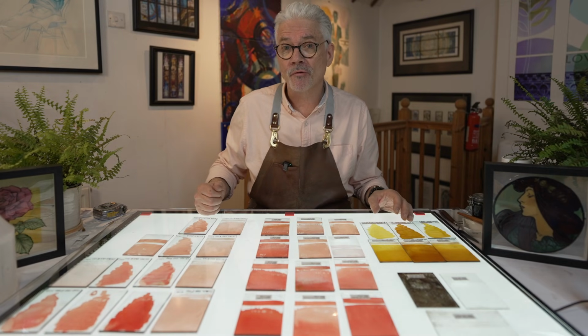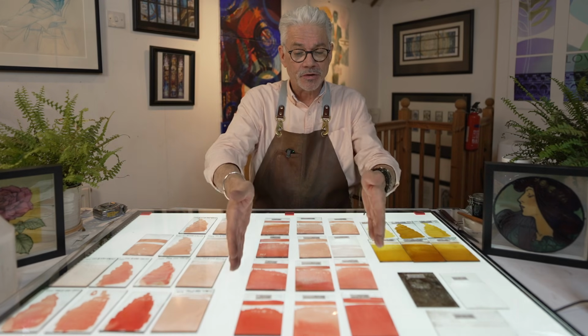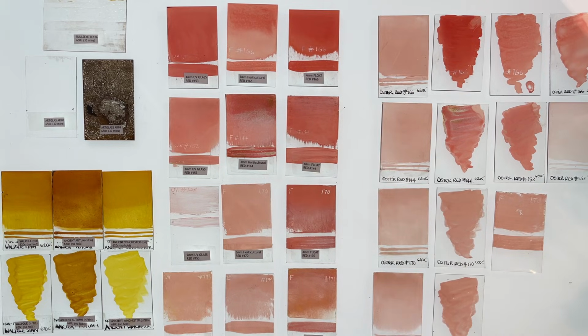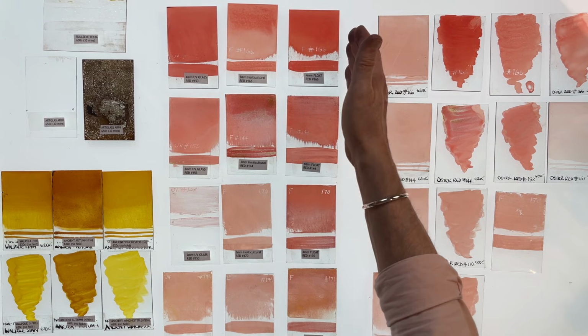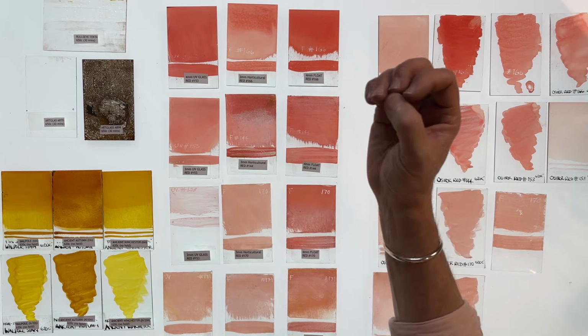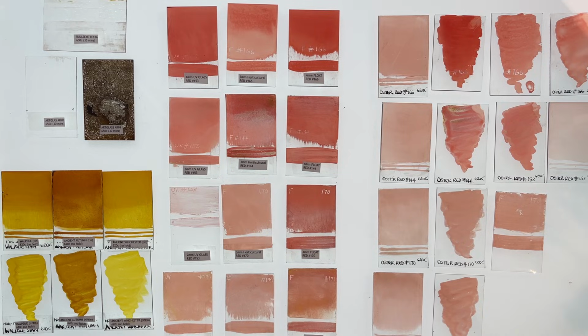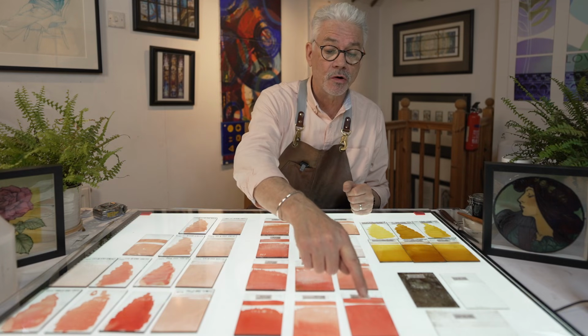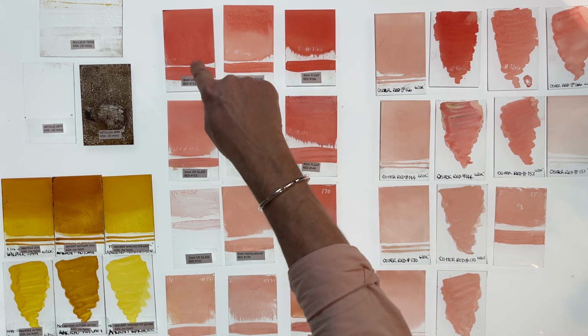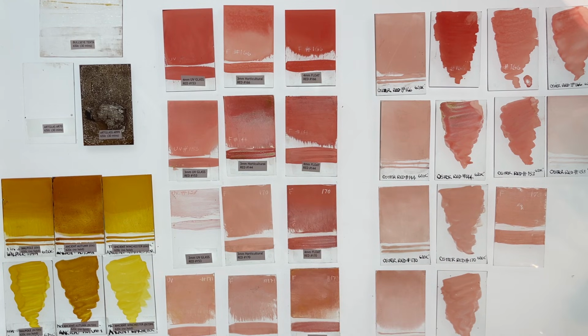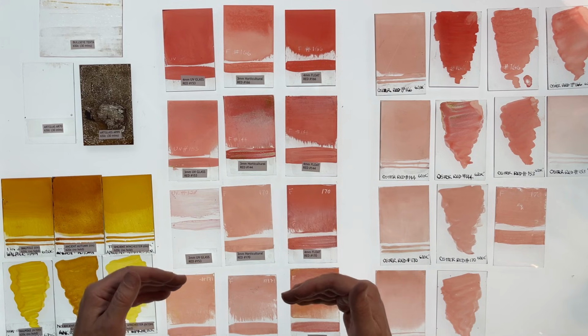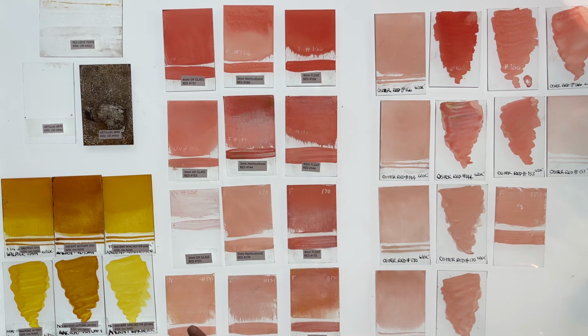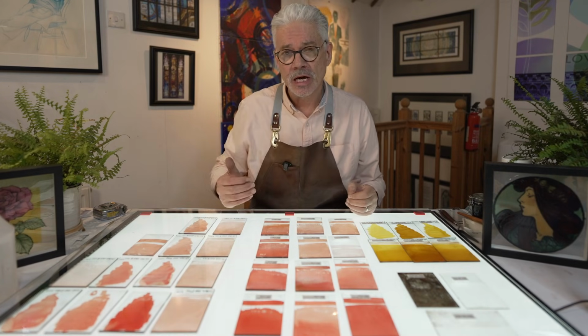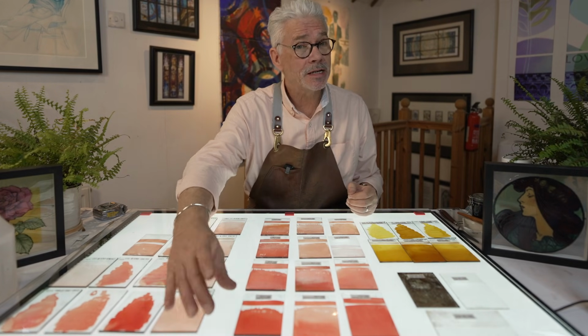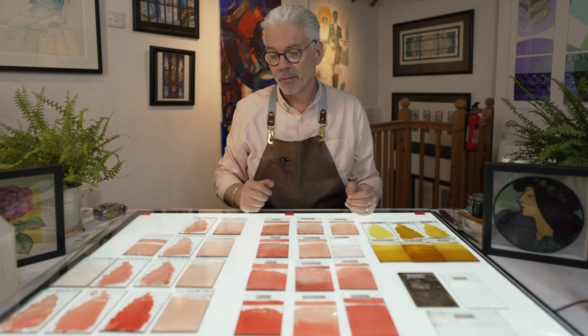With regard to the red stains, these are the best results by far. The 4mm float, the Pilkington's 4mm float is the clear winner with this beautiful, intense blood red using the red 166. Also great results on standard UV glass, 4mm UV glass, which gives us beautiful results as well. Coming down here to the 2mm glass is not quite as strong a reaction, and I think it would certainly suggest from these experiments that 4mm glass reacts better to the red stains than 2mm glass here.